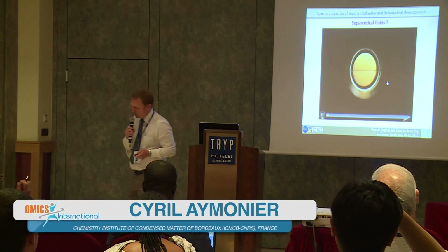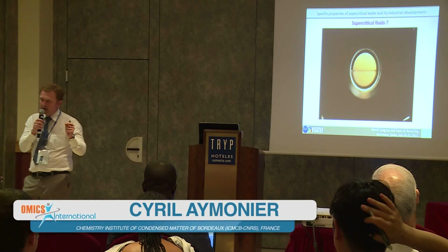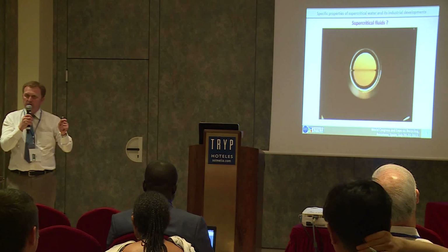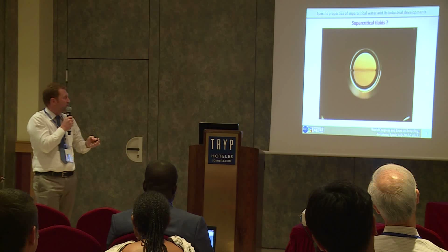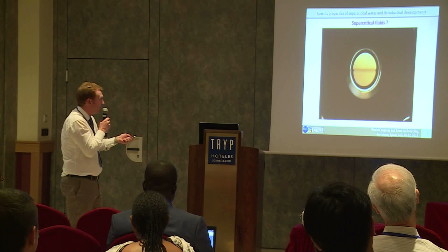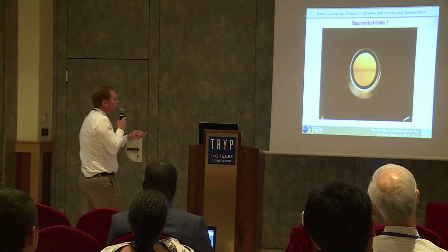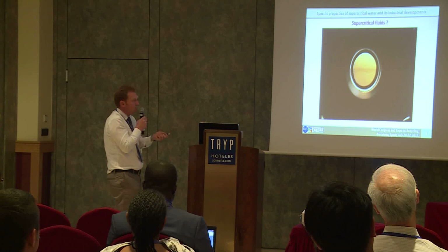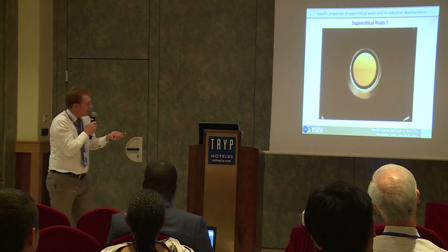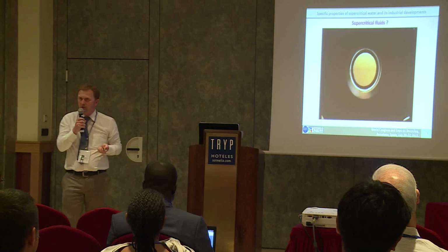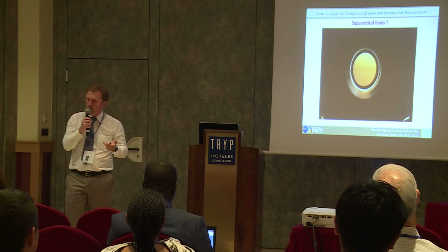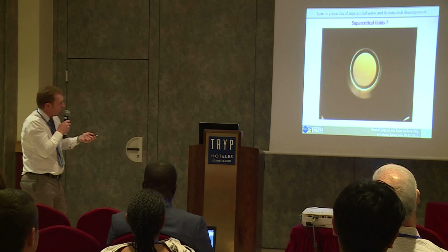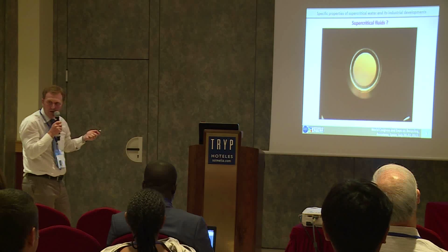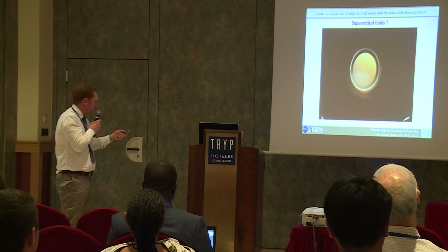Supercritical CO2 is easy because the critical temperature is 31 degrees Celsius. So we are heating the cell. We speed up the movie a little bit. The meniscus is disappearing, and you see we are homogeneous. We are in the supercritical condition. It seems to be homogeneous, and this is generally what people say.